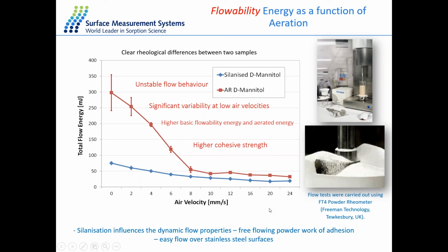We can also relate this to flowability properties. With the as-received D-mannitol, we're seeing very unstable flow behavior. In this case, we're looking at different air velocities. At very low air velocities, we have very unstable flow behavior for D-mannitol, which we don't see for the silanized material. This is due to the higher surface energy correlating to higher work of cohesion, which can have a poor effect on flowability. However, as you increase the air velocity, you're overcoming this cohesive effect and therefore have a much more stable flow. With the silanized D-mannitol, the silanization has caused quite constant and reliable flowability across the sample.